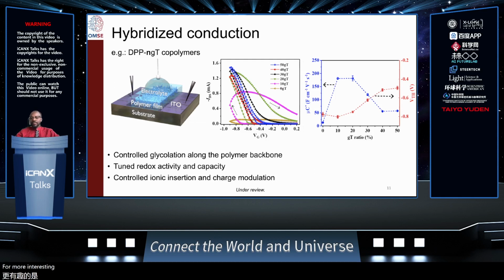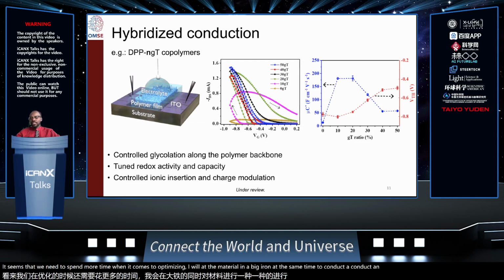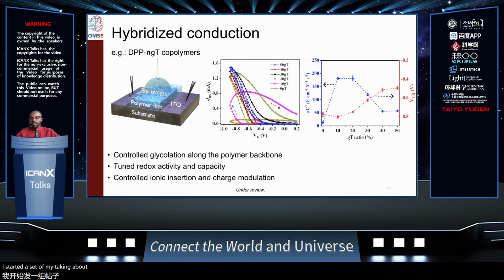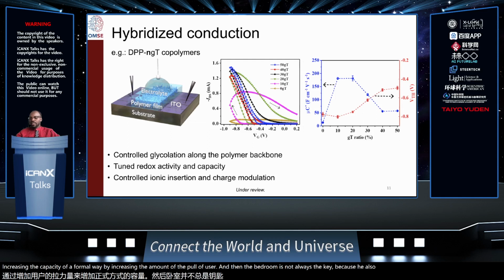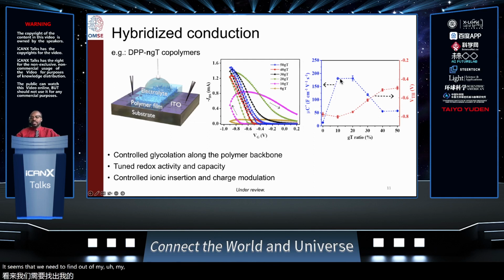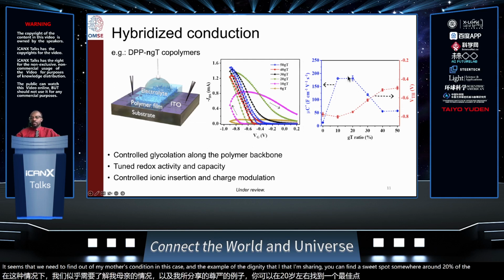But more interestingly, I'm showing this figure on the right, which shows the mobility-capacitance product, where it seems like we need to spend more time optimizing how well a material can uptake ions and at the same time conduct electrons. I started my talk talking about mixed ionic-electronic conduction, and this is where we need to find the sweet spot. It seems that increasing the capacity of our polymers by increasing the amount of polar groups along the backbone is not always the key, because we're also sacrificing how well the polymer is able to conduct electrons. So we need to find optimized conditions. In this case, the example of the DPP that I'm sharing, we can find a sweet spot somewhere around 20% of the backbone being functionalized with polar groups.